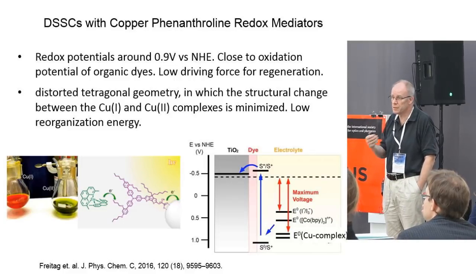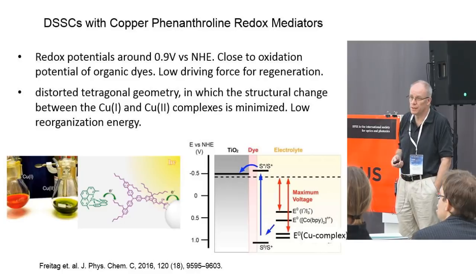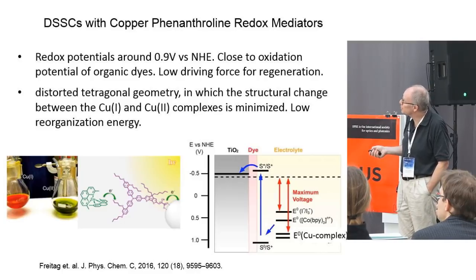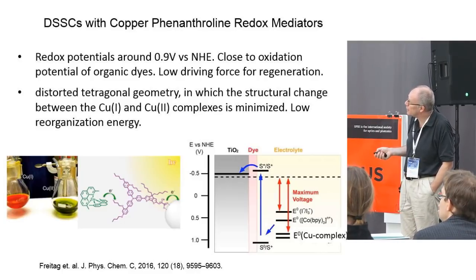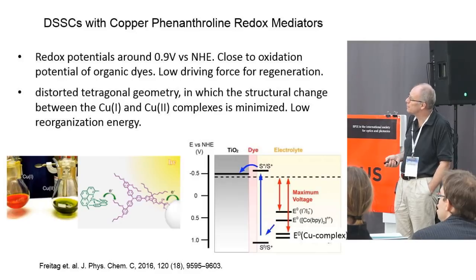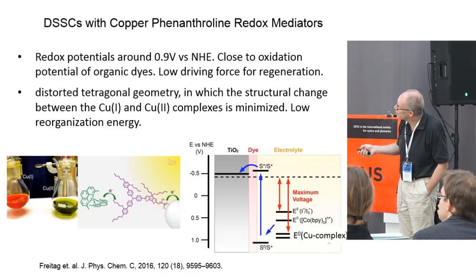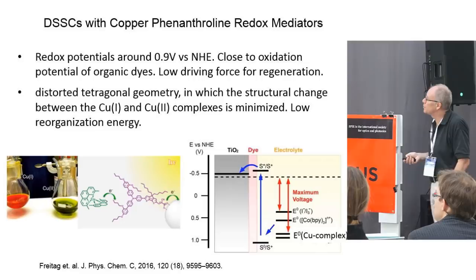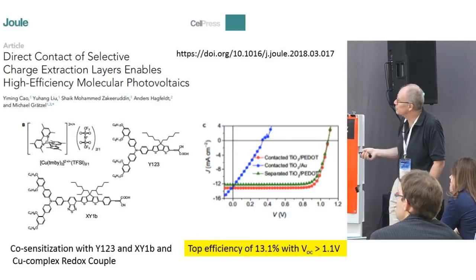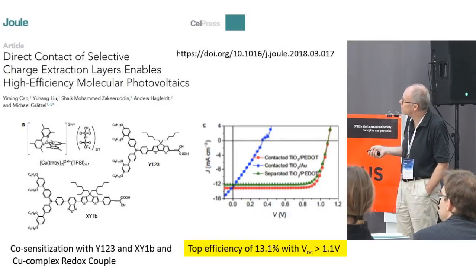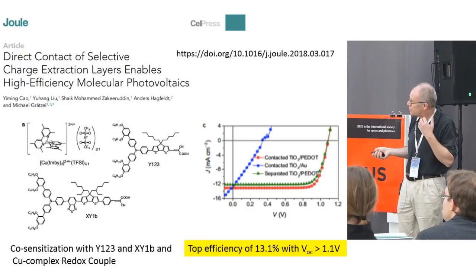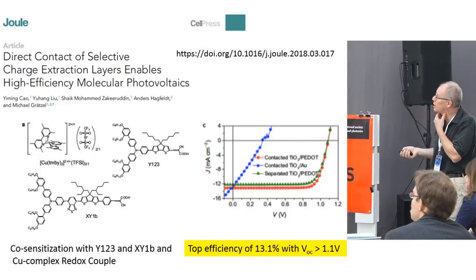So we get voltages much higher than the iodide. And the reason we could do it is design of the dyes to passivate recombination. So this is a typical organic dye we are using. So that's what we are doing at the moment, and our published record value nowadays is 13%. We are trying now to certify that to show that we have a new world record.